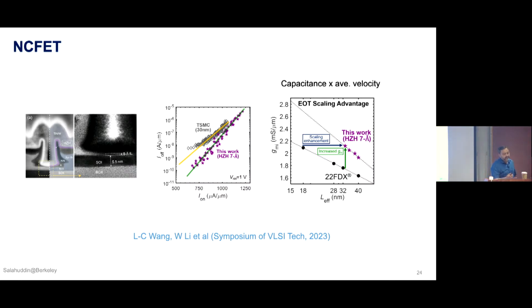And we can get higher on current and lower off current. We are getting this simply because our capacitance is higher, and so the charge is much higher. If you look at this quantity that we often call the transconductance, it's essentially capacitance times average velocity. You can see that effect as we reduce the channel length. This is 22FDX, which is a GlobalFoundries technology commercially available. This is how its trend looks, and this is how our trend looks. So at a much longer channel length, we can get the same kind of transconductance that is obtained in a commercially made technology. This is where EOT scaling gives us an advantage.